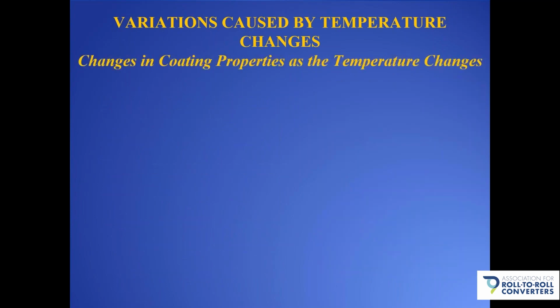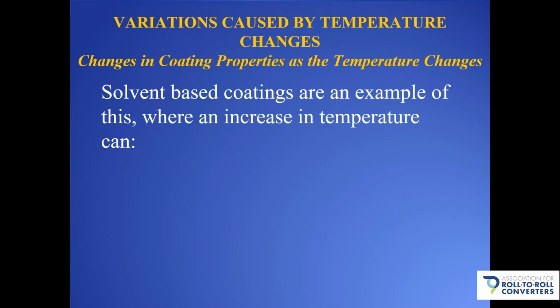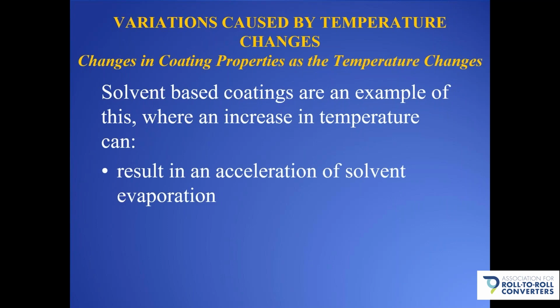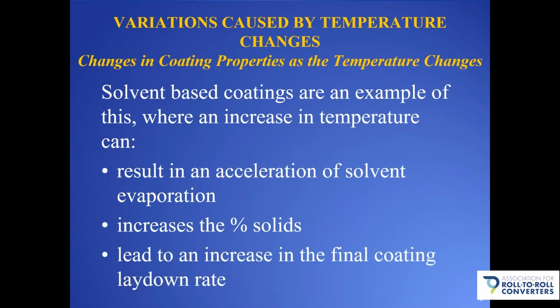Another issue that arises from temperature changes is changes in the coating properties. We could have talked about this when we talked about changes in coating, but we decided to put it in changes regarding temperature. Let's talk about a solvent-based coating, where an increase in temperature can result in an acceleration of solvent evaporation, which will result in an increase in the percent solids, which will lead to an increase in the final coating laydown rate.